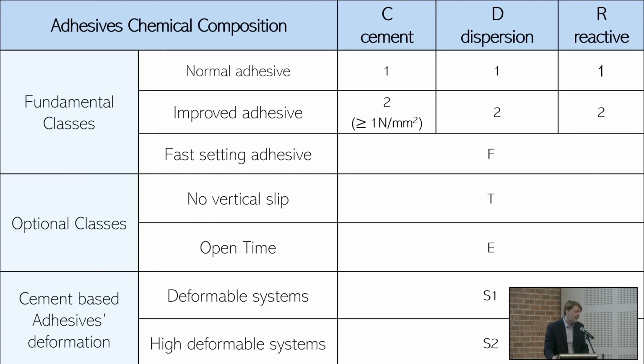So you may already understand that often when there is a problem on the floor, on the wall, it is not up to the adhesive. Maybe it's up to the application, but the performance of the adhesive is studied to guarantee the proper fixing. So the C2 adhesive is 10 kilograms. It is 1 Newton per square millimeter, so 10 kilograms per square centimeter. The class 1 is half of that, so 0.5 Newton or MPa, whatever it is.